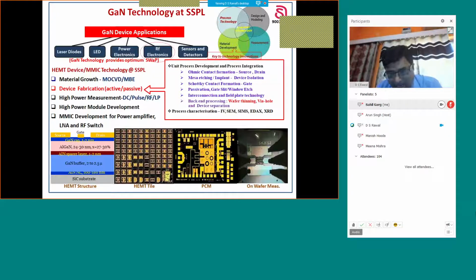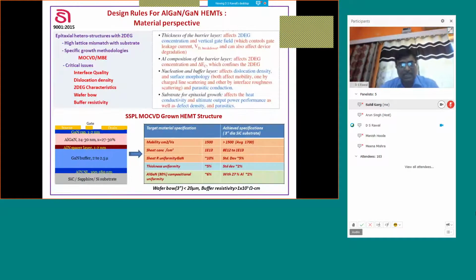And once you have your own active device, you have to have your own passive device with their models, and then these models are used for the designing of MMICs, which are the actual products used in these defense applications which I have just discussed. So the first important thing is your own material. The HEMT structure is very important, and it is a heterostructure between two different band gap materials. So one is AlGaN, another is GaN, and the 2DEG density, as discussed by Professor Dipankar, depends on the thickness of your barrier layer, that is the wide band gap material, aluminum gallium nitride.